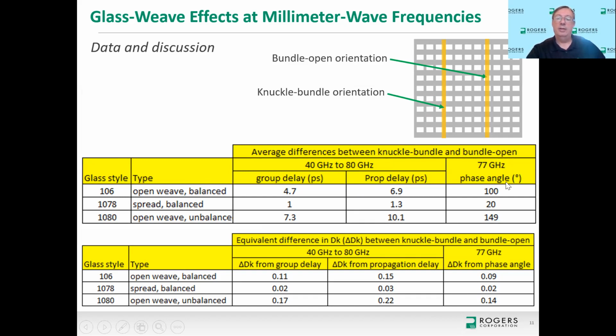And at 77 gigahertz for the 106 glass on the first row, I saw a phase angle difference between these circuits of 100 degrees. 100 degrees phase angle difference at 77 gigahertz is considered significant, especially for automotive radar. And that difference is really the difference between the exact same circuit, same material, same everything, except the circuit was aligned to the knuckle bundle and another circuit was aligned to the bundle open. And that is the phase angle difference I see between those two circuits.